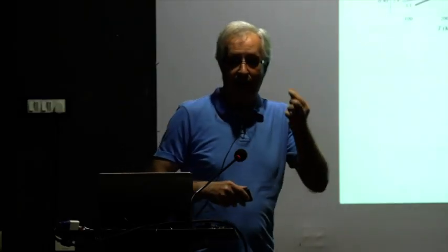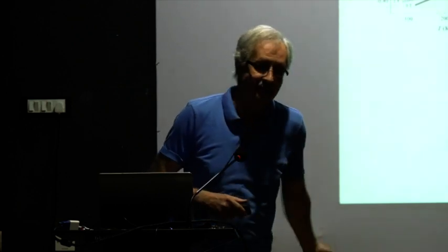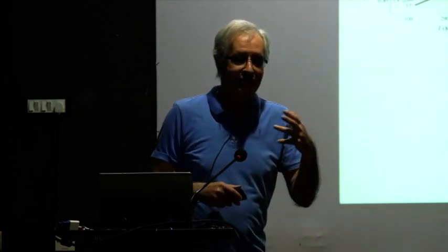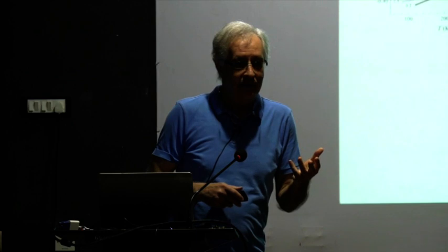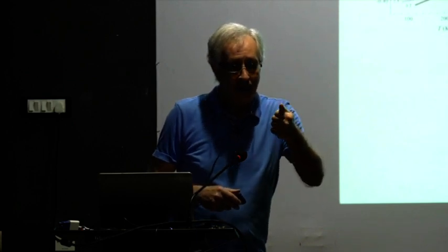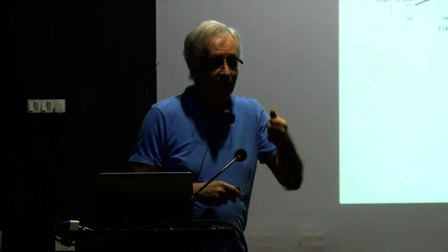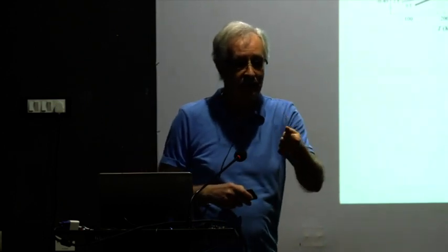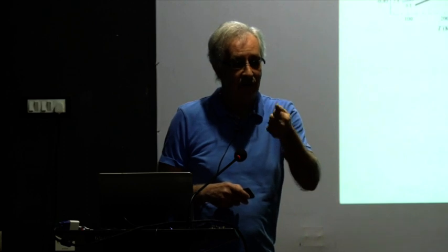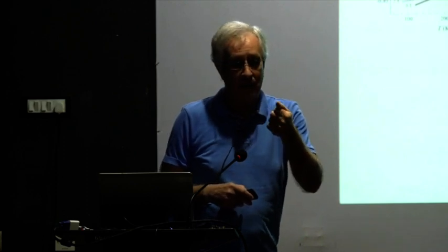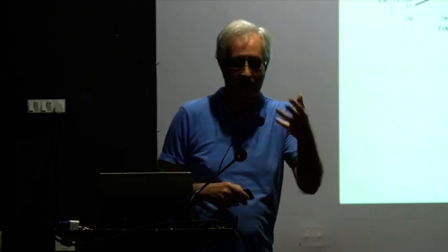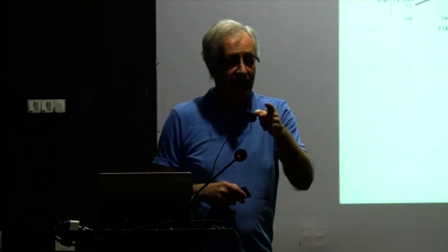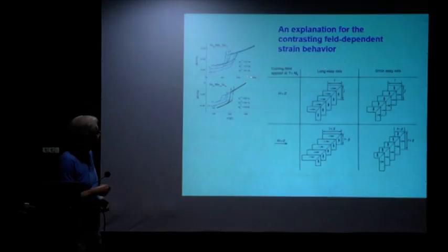So at the end, what is the strain measurement telling us? These kinds of strain measurements are telling us something very indirectly and something very unexpected, that as a result, we can give an argument on the easy direction of the magnetization, that is the magnetic anisotropy direction, not the magnetic direction, of course, but in which plane the magnetic anisotropy is the highest, just by looking at these.